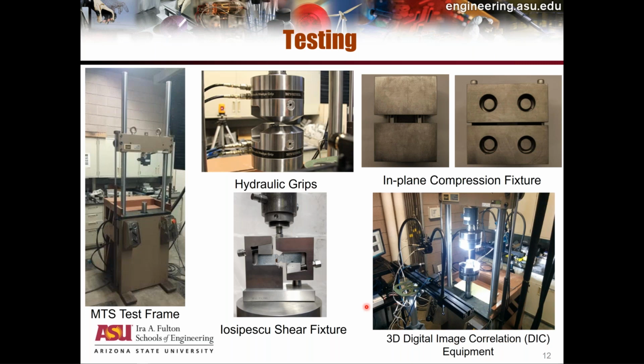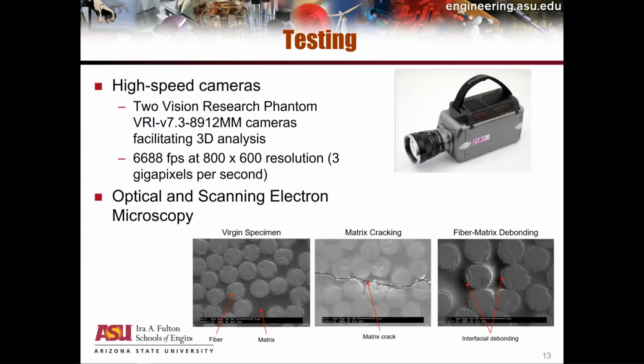In addition, we have high-speed cameras that we use to capture events where the duration of the event could be just a few milliseconds. We have used this to test Kevlar, which I'm going to discuss a little bit as a part of the engine containment system. So we take a piece of Kevlar, put it in a hydraulic system, pull it at a very high rate, use this camera, get the strain field, and then do the data analysis.